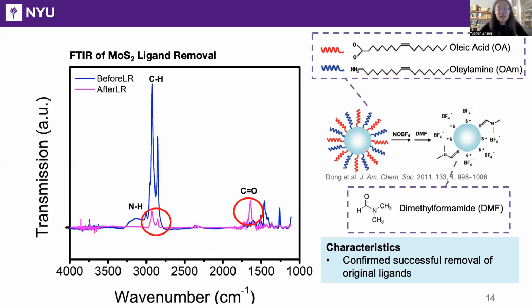Moreover, a new peak at around 1700 is the vibration of the C=O group, which is assigned to DMF molecules. This could also explain the high solubility and stability of the nanoparticle dispersion in DMF.